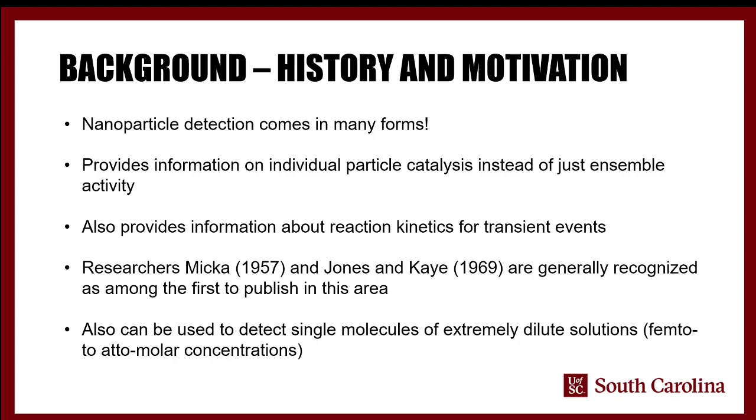So let's say you've invented a new catalyst. You put it into a batch reactor, and you notice that generally it works pretty well, but over time you see this consistent, let's say 20% loss of activity. And you study your catalyst, and you do X-ray photoelectron spectroscopy, and you do X-ray diffraction, and you can't tell any actual difference for the most part.